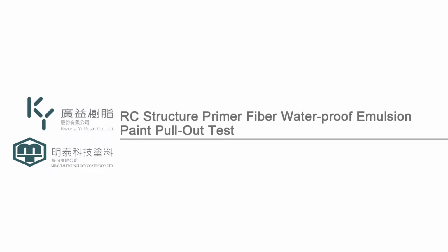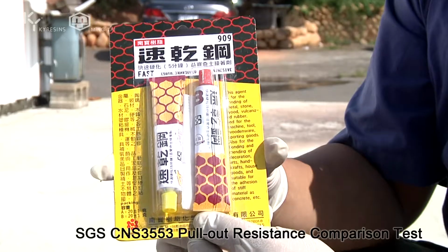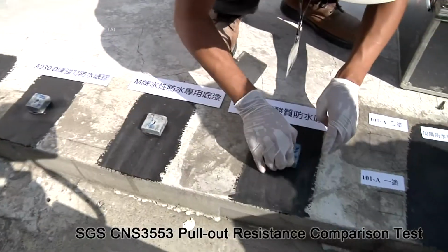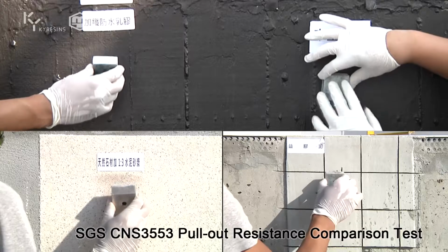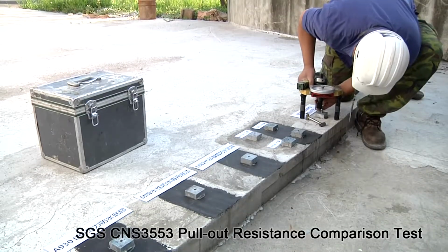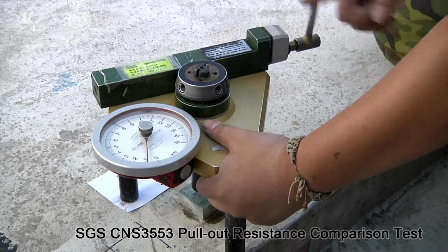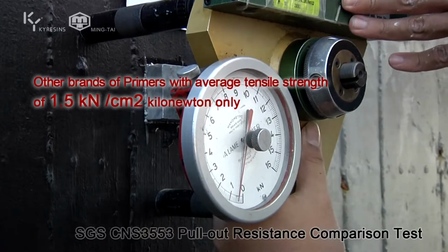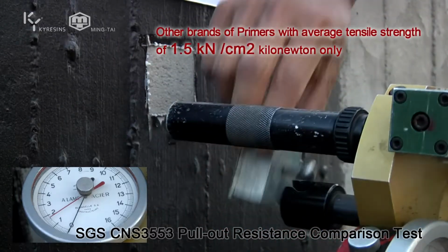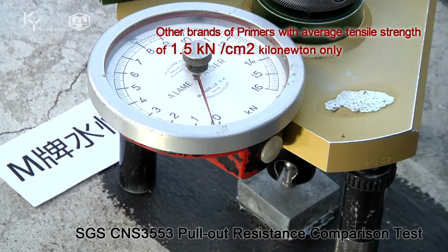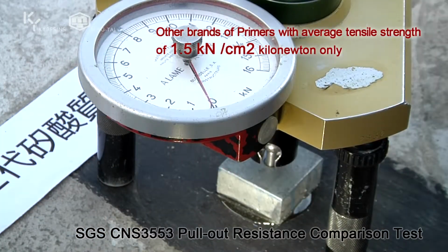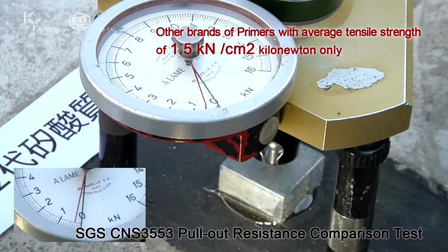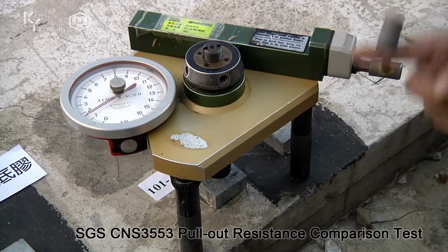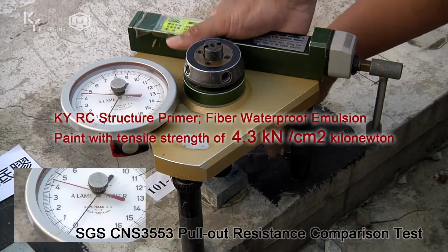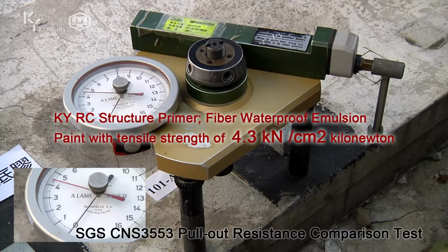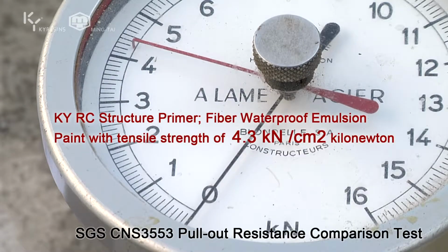RC Structure Primer Fiber Waterproof Emulsion Paint Pull-Out Test. According to the pull-out test by SGS in compliance with CNS 3553 standards, most of the waterproof materials and primers available in markets only had sufficient tensile strength of 1.5 kN per centimeter squared, whereas the dust and stains on the surface coatings would affect the second phase construction structures. However, KYRC Structure Primer and Fiber Waterproof Emulsion Paint stood out with an excellent tensile strength of 4.3 kN per centimeter squared.